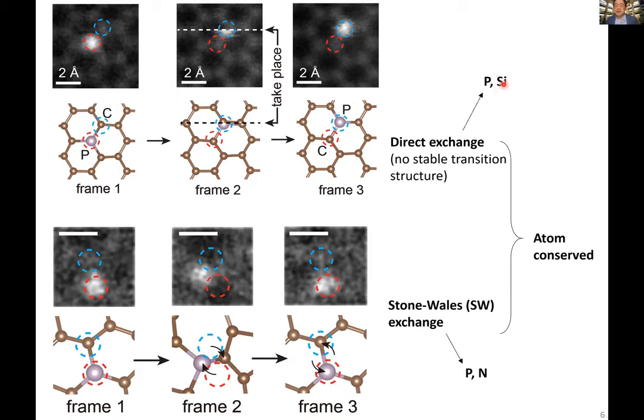And very interestingly, this never happens when we aim the electron beam at phosphorus, because when you do the calculation, it turns out that even though the electron energy is 60 keV, 60,000 electron volt, because it's such a light mass object, it doesn't give much energy to a heavy mass atom. So it only gives more energy when the atom is carbon.